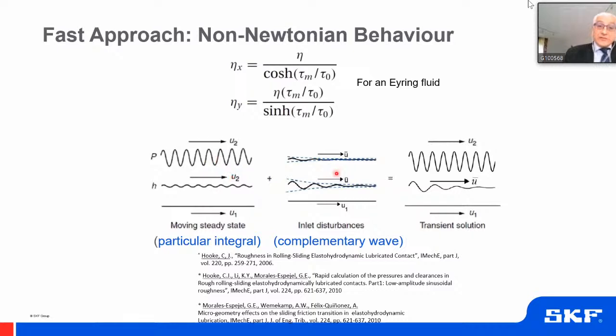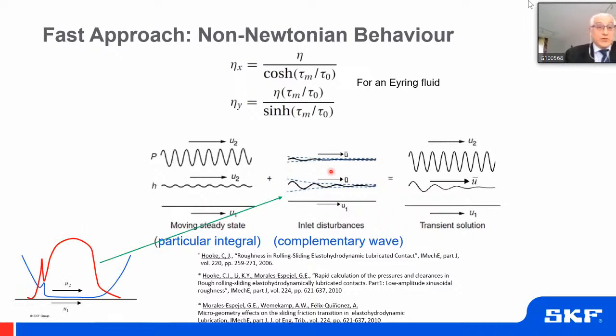There is another very important element that at the beginning we ignored, but then we realized that it's important, and that is the disturbance of the flow introduced by the roughness every time a ripple gets into the contact. It will produce some flow variation that will travel through the contact with the mean speed of the lubricant. Adding those two together, we get the full solution of the problem. A lot of the work on this is due to Professor Hooke from the University of Birmingham, who has been really working a lot trying to develop these complex models.